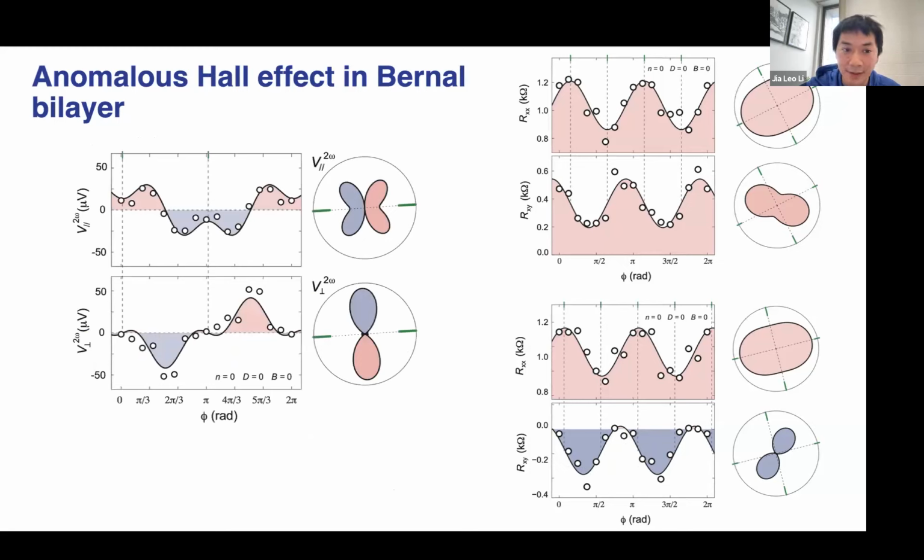At this point, indeed, if we were to measure the angular dependence of a non-reciprocal response, it does show non-reciprocal response. It shows rotational symmetry breaking, this one mirror plane, right? And the fact that we have non-reciprocity means that there could be a momentum polarization in the electronic order, which is connected to the anomalous Hall effect.